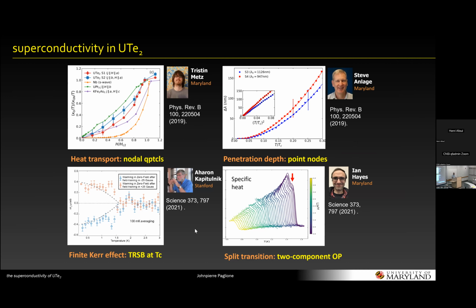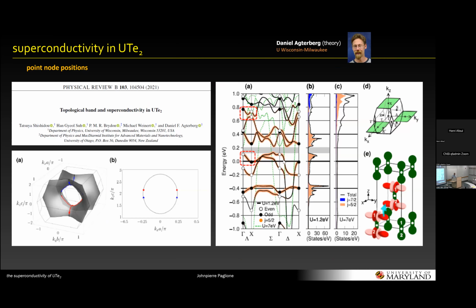So here's the sort of interpretation as of maybe 2 years ago, that there's a nodal order parameter, there's a quadratic temperature dependence of penetration depth in all directions, there's a Kerr onset suggesting time reversal symmetry breaking at TC, and there's an observation of a split pair of transition temperatures. And so that would all point to a two-component order parameter.